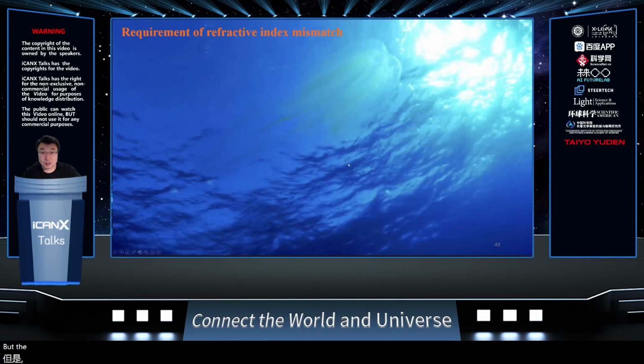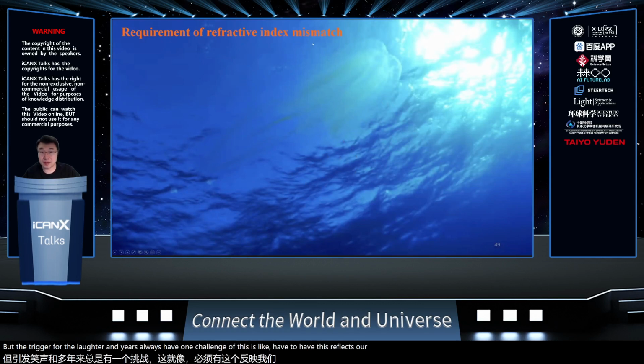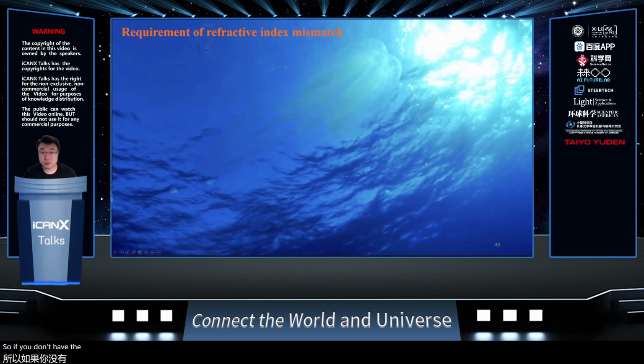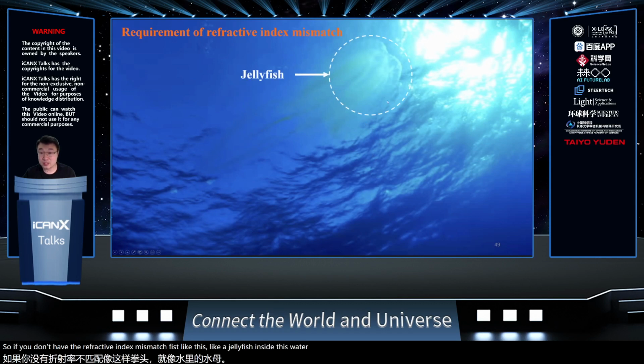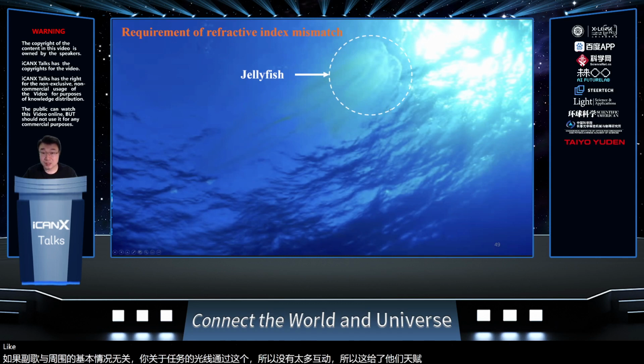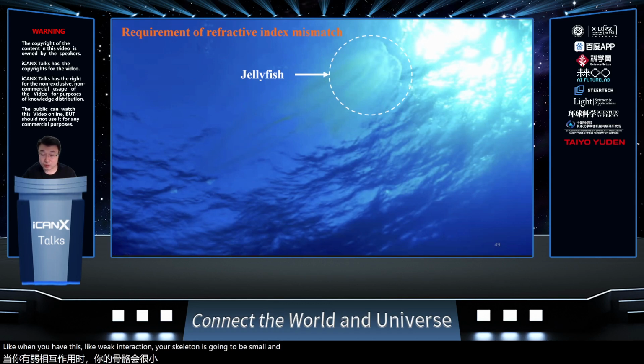But the tweezer for the last 20 years has always had one challenge, which is that you have to have a refractive index mismatch. As mentioned before, the tweezer is based on the interaction. So if you don't have the refractive index mismatch, just like a jellyfish inside water, if the refractive index is really matched with the surrounding, basically your light will pass through. So there isn't much interaction. This gives some challenges: when you have this weak interaction, your scattering is going to be small and your force is going to be small.